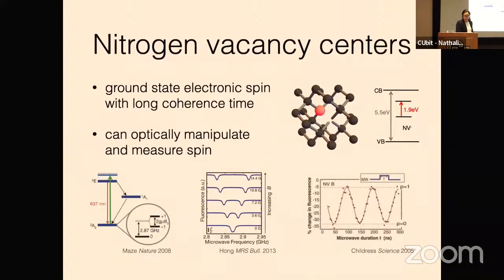Okay, so the physical platform that we are working on for nanoscale quantum sensing is the nitrogen vacancy center in diamond. Sorry, I can't actually see my slides from back there. So this is a substitutional defect in diamond. If I take the diamond lattice and take 2 carbon atoms out and then put in 1 nitrogen atom, then I have nitrogen next to a vacancy. And it turns out that this little color center has very, very deep defect levels far away from the valence and conduction band edges of diamond. And because of this, and because of the very large band gap and headroom that you have from diamond, you even have electronic excited states, orbital excited states that are also very far away from these band edges.